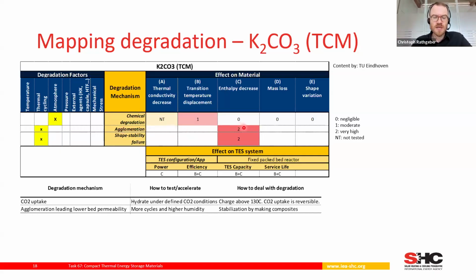This in turn leads to an enthalpy decrease on material level, and this then affects basically all of the properties that here were measured for a fixed bed packed reactor. So power, efficiency, capacity, all are affected by differences on material level. And a way to counteract, to deal with the degradation here, could be the stabilization by making composites of the potassium carbonate.